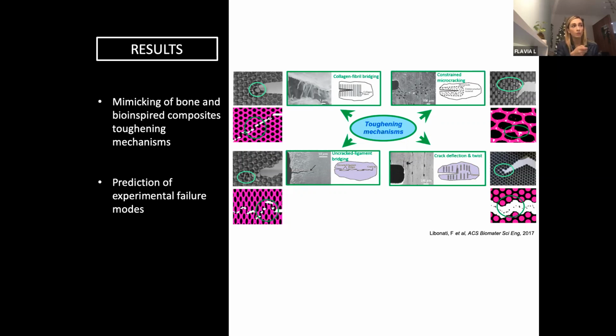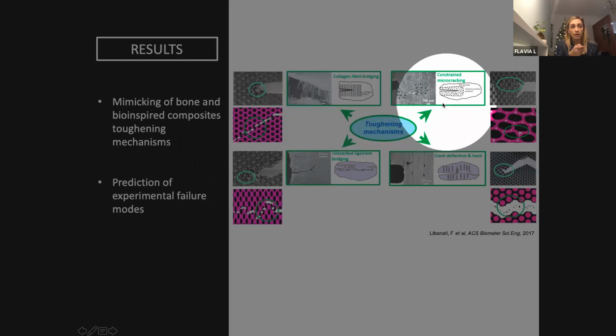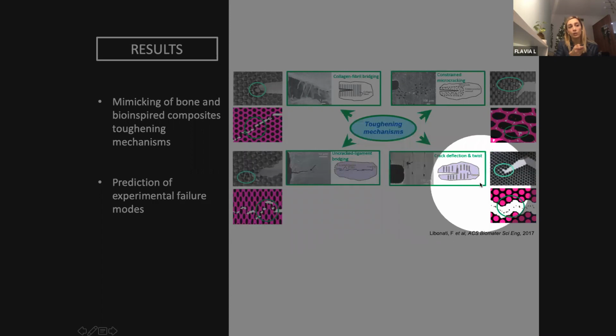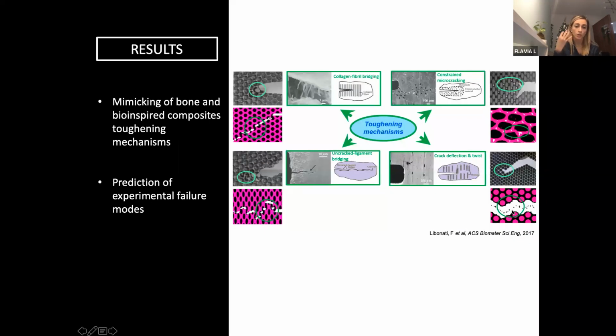So the collagen fiber bridging is mimicked through a soft polymer fiber bridging. The constrained micro cracking, which is the formation of these tiny cracks in front of the crack tip. Then the uncracked ligament bridging, and then the crack deflection and twisting, which is probably the mechanism which mostly contributes to the dissipation of energy and then to the toughness enhancement.